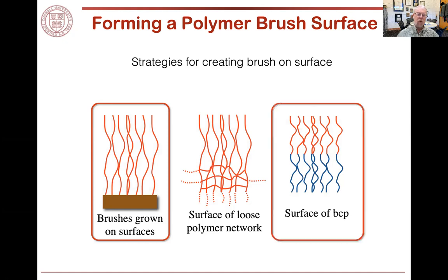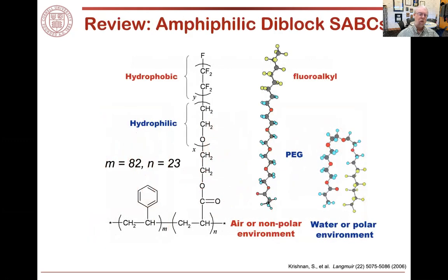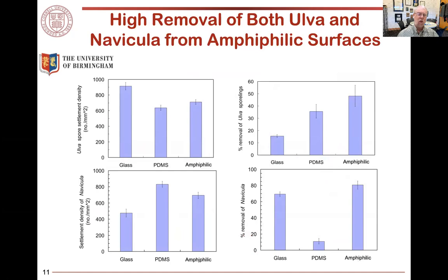But for our purposes, as we carry out fundamental studies, we found that block copolymers, with their ease of attachment and their ability to form physical crosslinks, are extremely effective in letting us test different brush-type architectures. We first demonstrated that with an amphiphilic material, a combined fluoroalkyl and PEG unit that had both polar and nonpolar function, and was very dynamic. Against species that like to settle on polar surfaces and species that like to settle on non-polar surfaces, the amphiphilic surface gave effective fouling release of both types of fouling species.